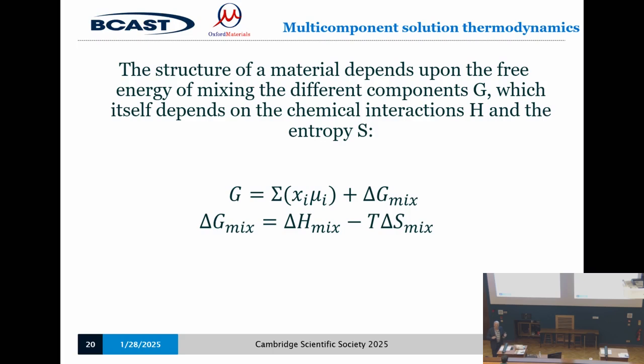Now, we can understand what happens. When you take copper and mix it with a little bit of tin, everything is dominated by this. The same when you mix a bit of carbon into iron. So beyond a very small amount, you start to get compounds, which is good at first because it helps you tweak up the properties by adding little bits of stuff into the material. But if you add too much, forget it, because you start to get loads of compounds and it's a mess. It's a material that breaks up and you can't make it into anything useful. But this term hasn't yet come into play because you're not adding enough.